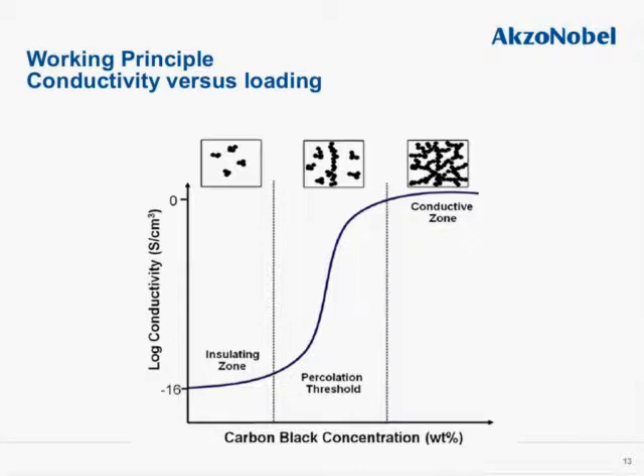And the first zone, the insulating zone, is also indicated in the picture above. When the carbon black is not dispersed, we have those pellets that are isolated in the polymer matrix. They cannot reach each other, so therefore the electron cannot move around. As soon as the percolation threshold concentration is reached and the conductivity starts increasing, some of these carbon black networks are in direct contact with each other or close enough that they can ensure the electrons jump, so therefore electricity flows. And this increasing conductivity goes exponential. So as soon as they start connecting, the circuit is essentially established.